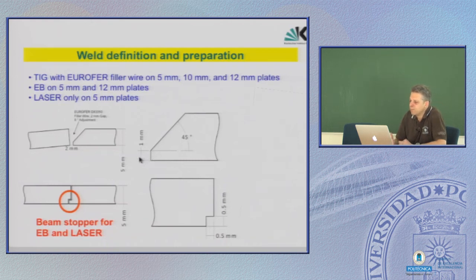The problem with beam welding is that if the beam is too strong or has too much power or is too long on the same spot, then the beam goes completely through both parts. And so it produces, especially if you weld pipes or cooling structures, material which goes into the cooling channel. That's why we tried to stop the beam by such a rectangular arrangement on top.